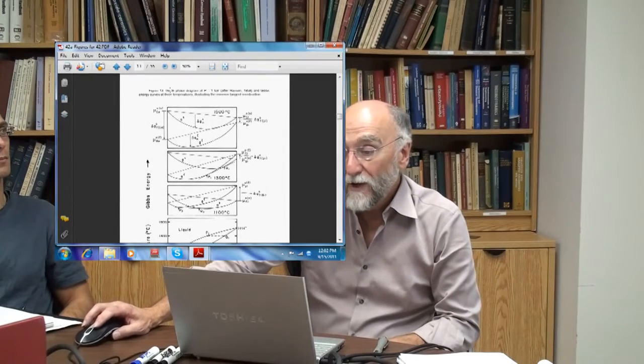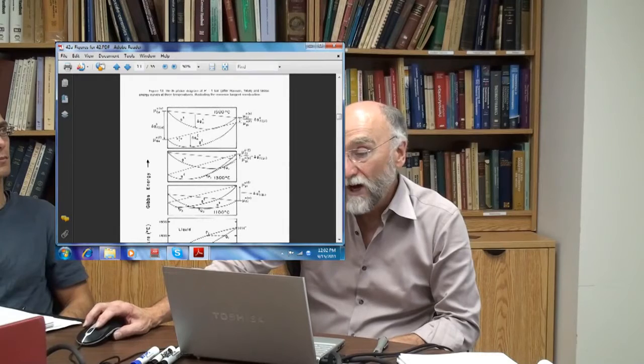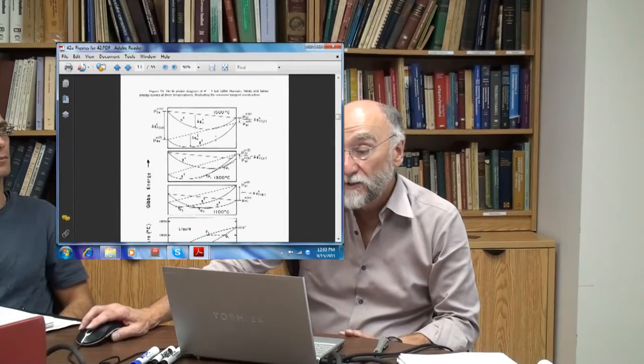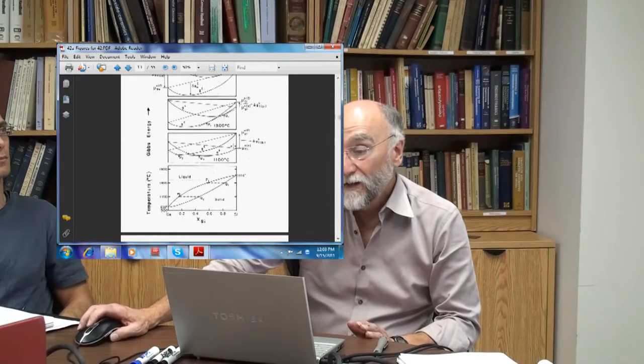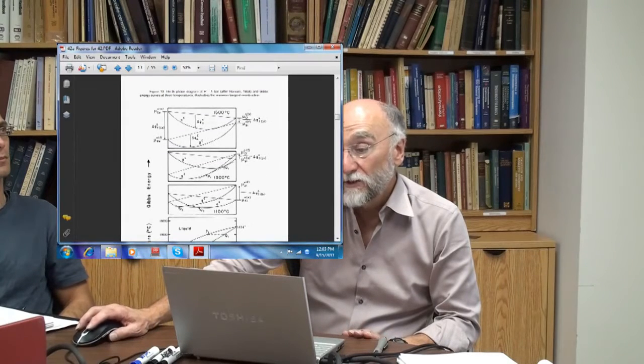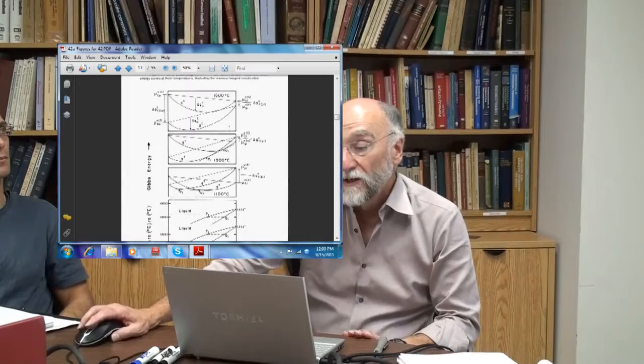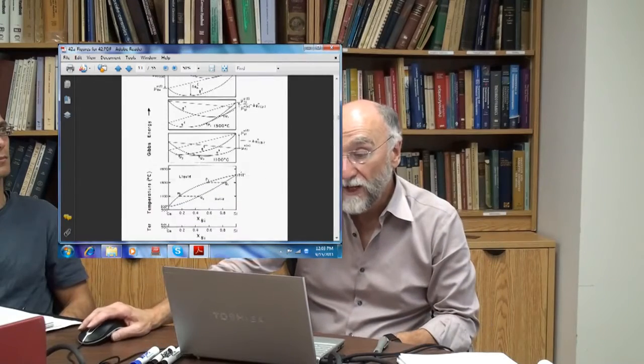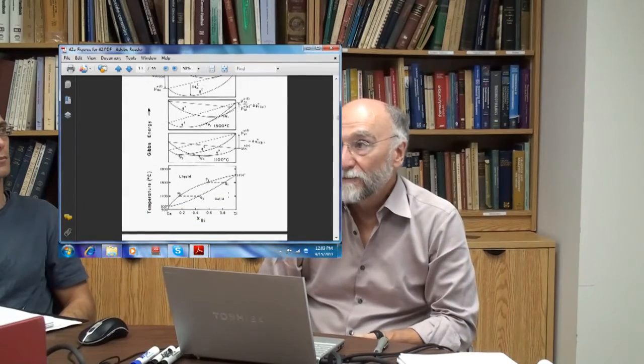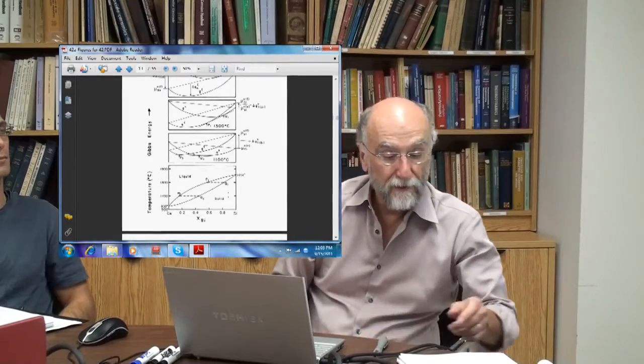Okay, so if you have reasonably convex looking Gibbs energy curves like this, the main effect is that as one descends through the other, the chemical potentials give the Gibbs energies of fusion change, and this then generates this lens-shaped phase diagram. So that's the basic thing.